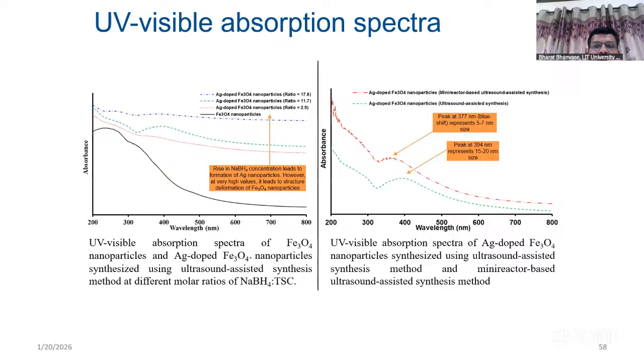And if you see the UV spectrum, you will observe the Fe3O4 nanoparticle spectrum, which is prepared in different cases. One is Ag dope Fe3O4 at different ratios here, that is sodium borohydrate to citrate surfactant ratio that we have tried. And the peaks which are essential there, that is peak at 277 or you can say 394. So that represents the formation of this material successfully.